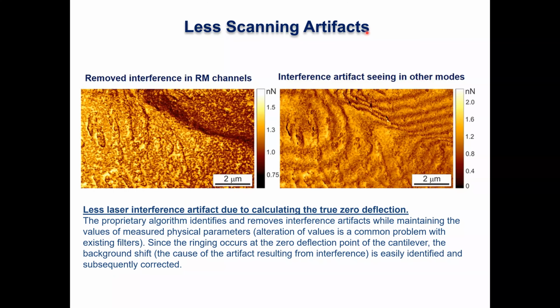So another thing, less scanning artifacts. For example, if you just use regular imaging of adhesion, and that surface might be reflective, you can see well-known interference artifacts. And it can be a kiss of death for any quantitative interpretation of this. So we specifically remove these interference artifacts in ringing mode, because when you do ringing, you can clearly see the zero force. And this is what is needed, and this is what is disturbed when you see these interference artifacts.